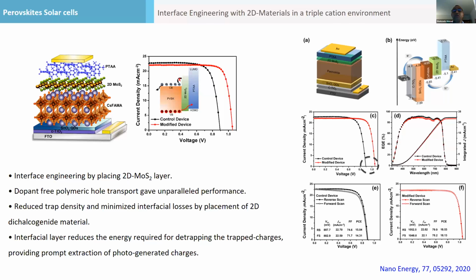So by placing the MoS2 layer, we can engineer the interface. And the good thing is that this PTAA was dopant free. So dopant-free devices always give you less efficiency, but they are more stable. So we use a dopant-free polytriarylamine, PTAA, but we use an MoS2 layer on top to increase the performance. And what we noted is a reduced trap density and lower interfacial losses. And there was low energy required for trapping and detrapping of charges, which provides more efficient extraction of photogenerated charges. The device also gave a higher voltage, a higher performance, and higher stability.